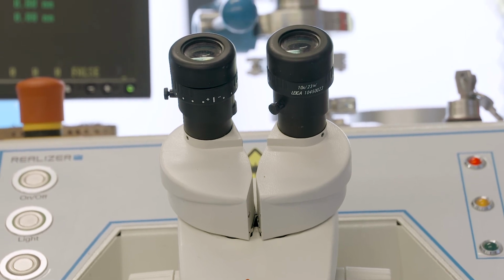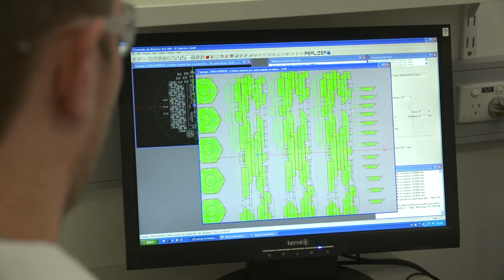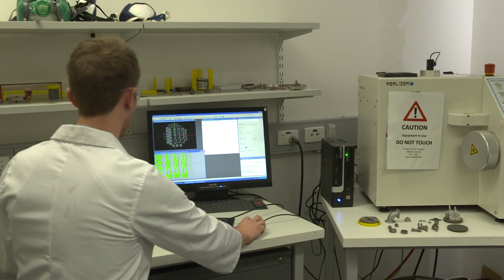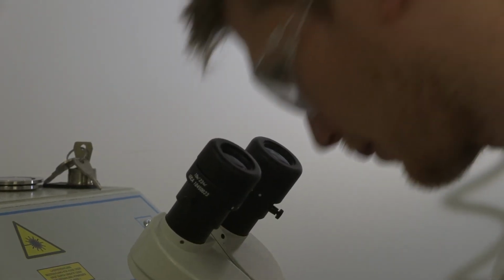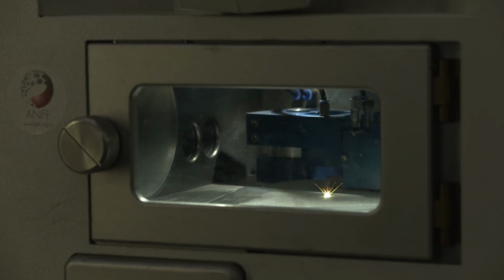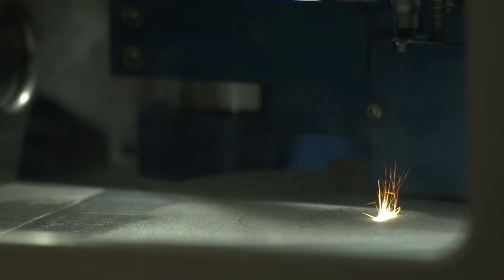And it obviously, like all 3D printing, builds things up layer by layer, but how does this actually work? So the starting material is metal powder. The powder has been atomized to be spherical particles between 25 and 65 microns in diameter. In the case of this machine, the powder is screeded across a build tray, and the layer thickness is about 25 microns, and then a high energy laser with a very fine focus of down to about 10 microns starts to weld those particles together. So it rasters over the surfaces, welds the particles together, produces a layer. Build tray moves down 25 microns, the next layer of powder is screeded across, and then it starts stacking those sequential welds on top of each other.